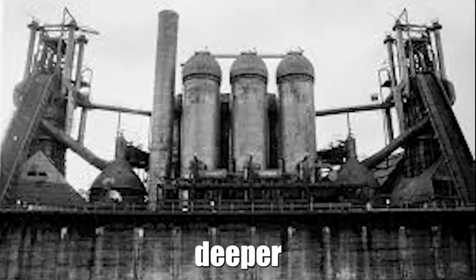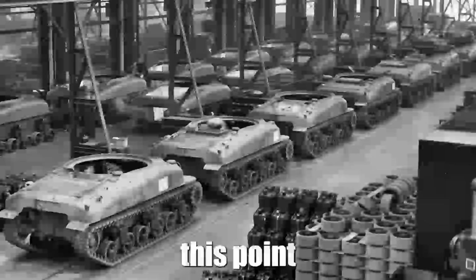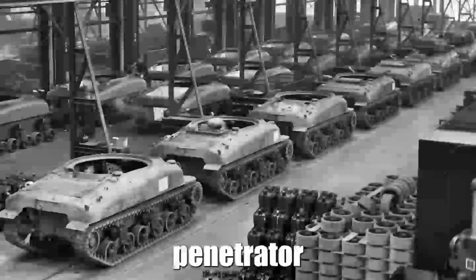As the projectile pushed deeper into the plate, it encountered gradually decreasing manganese content. But by this point, the projectile had already lost significant energy to deformation of the surface layer. The lower manganese backing steel, while more brittle than the surface, still possessed adequate toughness to resist the reduced energy penetrator without catastrophic failure. Standard specification plates, with uniform low manganese content throughout, offered no such progressive resistance. The projectile impacted brittle steel that fractured rather than deformed, allowing the penetrator to maintain its shape and momentum all the way through the plate thickness.